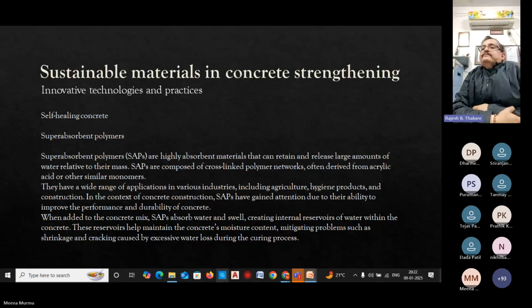When added to a concrete mix, SAPs absorb water, swell, and create internal reservoirs of water within the concrete mass. These reservoirs help in maintaining concrete moisture content, mitigating problems such as shrinkage and cracking caused by excessive water loss during the curing process.